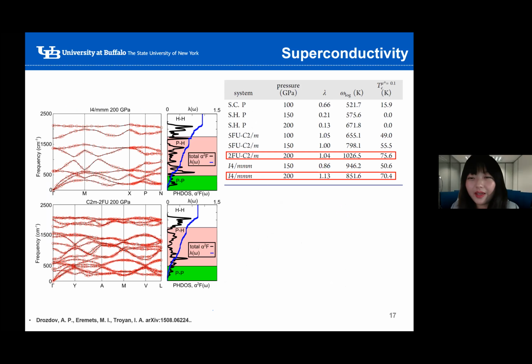So then we calculated the electron-phonon coupling parameters for them and estimated the Tcs. We would expect that at 150 GPa and below, the two formula unit C2/m and I4/mmm phases would have similar Tc values due to the similarity in their structures. At 200 GPa, the I4/mmm has a slightly bigger lambda, but smaller omega log.